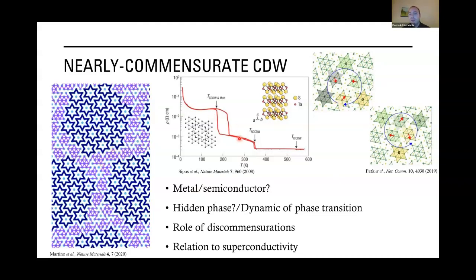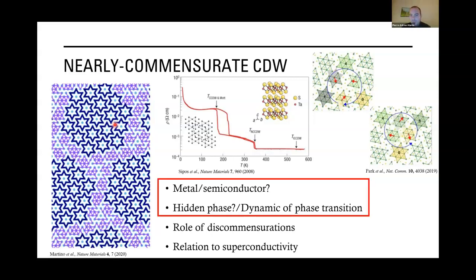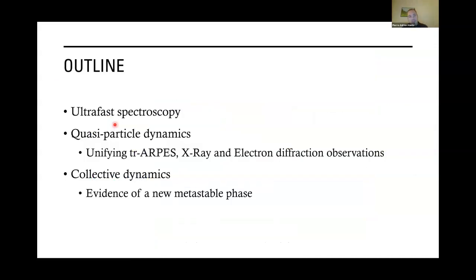However, if you look at the temperature dependence of the resistivity, it has more of a semiconductor type of temperature dependence. Similarly, there has been demonstration of the existence of a hidden phase or metastable phase driven from the commensurate phase. There has been some report of a metastable phase driven from the nearly commensurate phase, but these are scarce reports. And finally, like I mentioned previously, the link between this material and superconductivity only exists in phases with discommensuration. So these are the main open questions remaining in this material. But here we are going to mainly focus on these first two open questions.